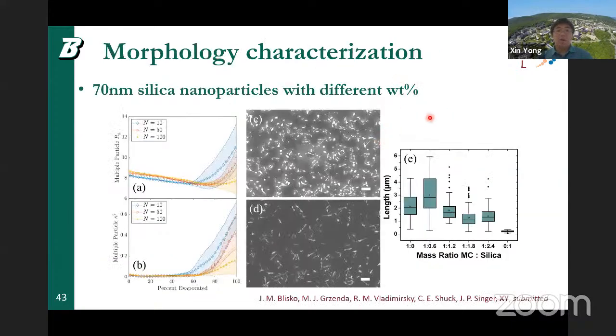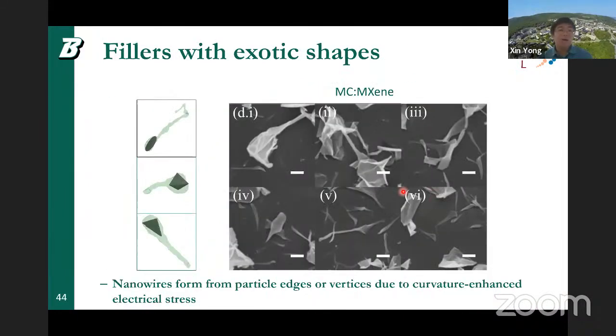And so we can also characterize the morphology, which is consistent with our simulation prediction in the experiment. And finally, we tried fillers with exotic shapes. One interesting observation that we found is that nanowires pretty much always form from the edges and vertices of these particles, which we believe is due to this curvature that enhances the local electrical stress, which facilitates the wire formation at the local point.